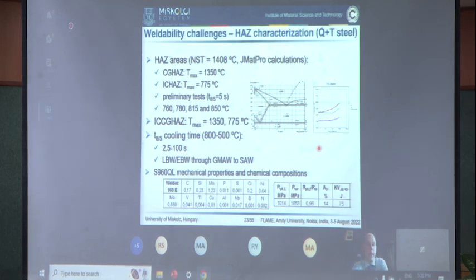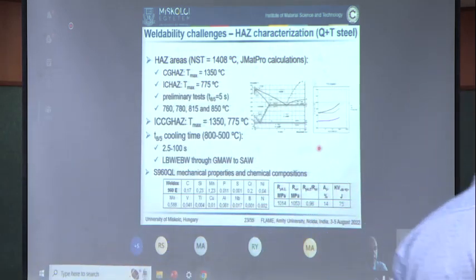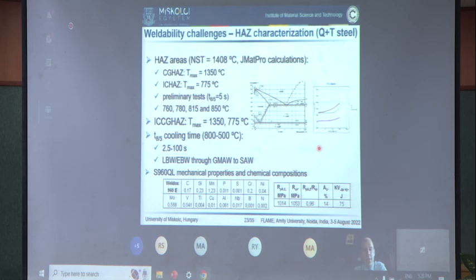For the coarse-grained heat-affected zone, we used a 1350 peak temperature. For the intercritical heat-affected zone, a 775 degree Celsius peak temperature, and we used a combination of them for the intercritical coarse-grained zone. We analyzed the characteristics of the heat-affected zone based on the t8/5 cooling time, which is very crucial in terms of welding, because this is the cooling time between 800 degrees Celsius and 500 degrees Celsius.